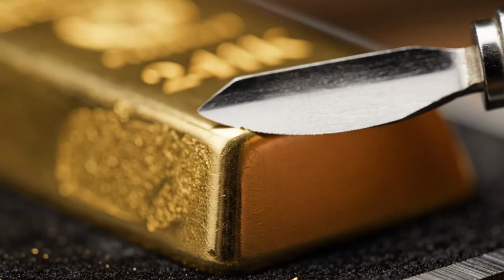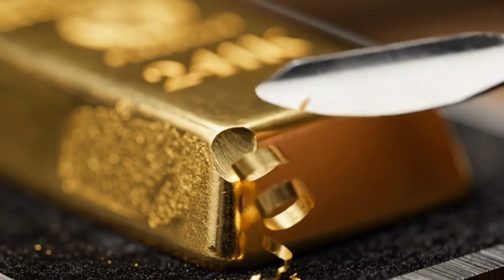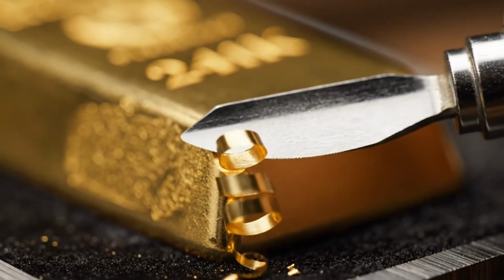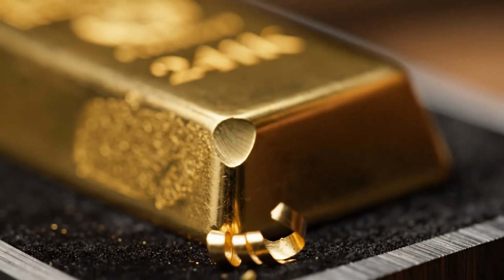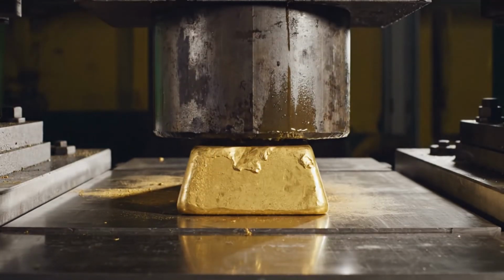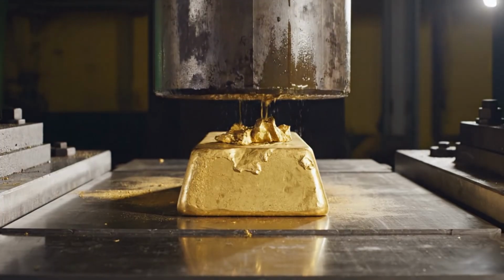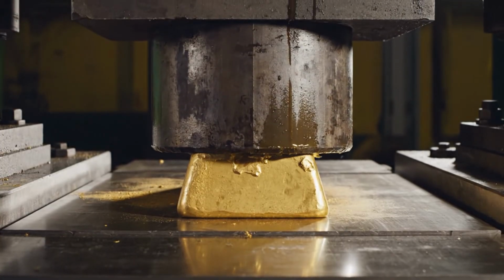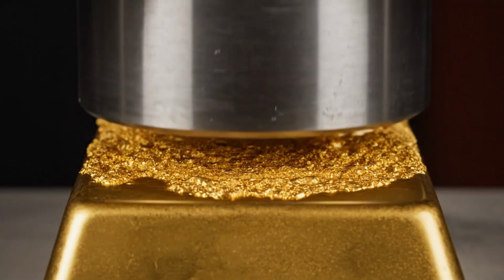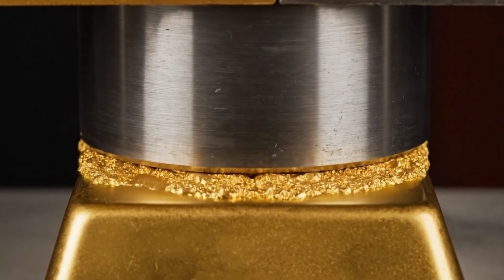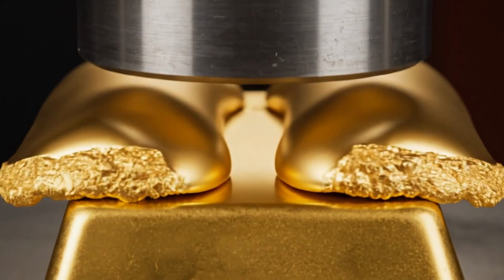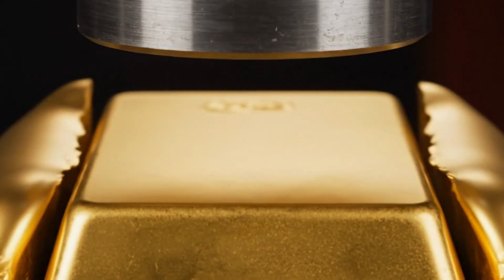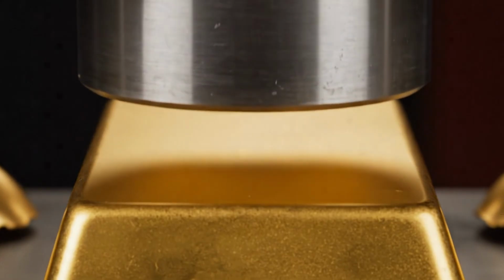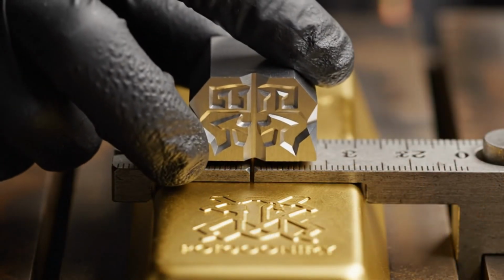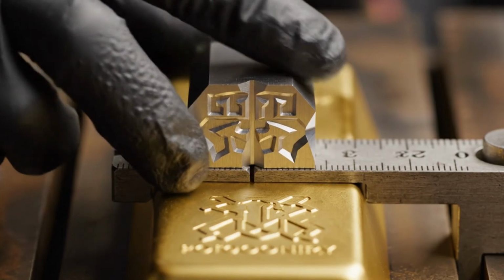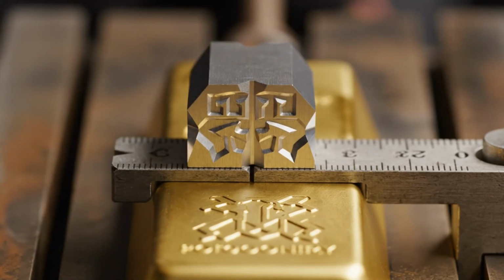If the weight is slightly over, we carefully shave off the excess from the corners, collecting every filing to be melted down once again. The surface must be perfectly flat for the hallmark, so we run the bar through a high-pressure press to smooth out any irregularities. A hydraulic press descends with immense force, flattening the top face into a uniform canvas, ready to receive the refinery's prestigious official seal today. Now we position the die for the logo, aligning it centrally to ensure the branding is stamped deep into the soft, malleable yellow metal.